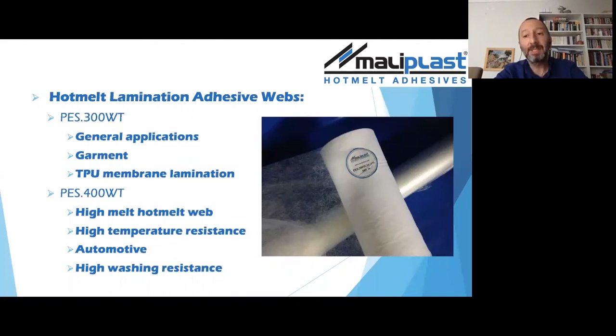For example, for the laminations inside of the cars, as you can imagine, in the hot climate countries, when you leave the car under the sun, inside of the car, the temperatures can reach even 100, 110 degrees, which is not that good for the hot melt lamination. Because when you are using thermoplastic hot melt adhesives, when you go over the melting range or near the softening points of the hot melt adhesives, the material can get delaminated. Polyester 400 WT gives very good performance with its high temperature resistance.